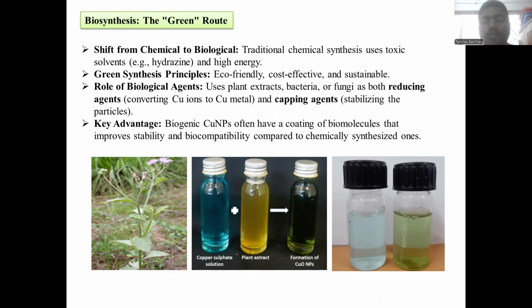So, to find the best source, we screened several local plants, including Tridax procumbens and various jujube species. While these plants showed some activity, they often resulted in unstable particles or slow reaction times. However, we achieved excellent results with Vernonia cinerea, commonly known as Sahadevi. The leaf extract of Vernonia acted as a superior reducing agent, giving us a rapid and stable color change, which led us to select it for the final synthesis protocol.